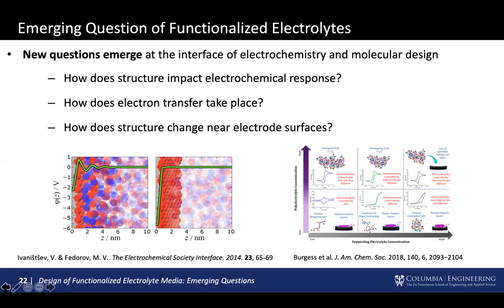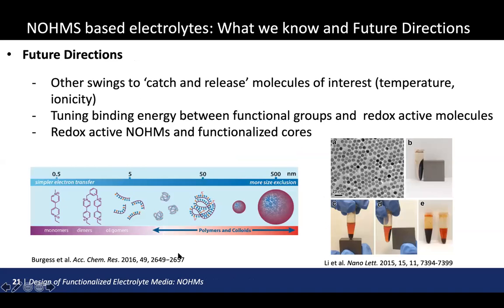Yes, 100%. I think those are all definitely important considerations. In terms of the point you mentioned, material utilization, it's very possible that when you have these large redox active structures, you can't always access all of the charge along that canopy. The research that has been done in redox active polymers has found that as a limitation, so that's definitely something to consider. And in terms of your second point related to the diffusion of these molecules, that's a really good point. These redox active species sound like a very promising concept to couple with non-selective membranes. But if we think back to the hexagon, there's a trade-off. We have molecular stability and reduced crossover, but the diffusion of those molecules is definitely lower than that of single ions.